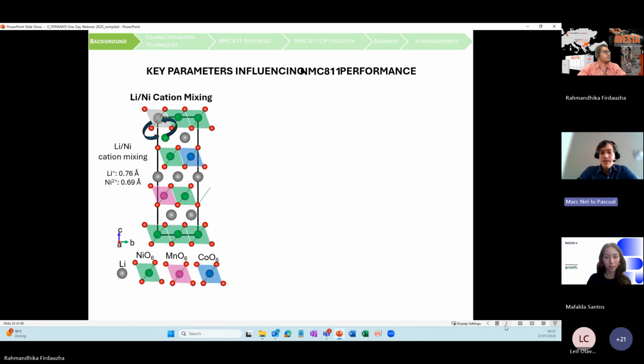Okay, there are several parameters that affect the performance of the NMC 811. And the first one is the lithium nickel cation mixing. This is an effect that occurs when the lithium and the nickel exchange positions in the crystal structure. This happens when the nickel is in a 2+ oxidation state, showing a similar ionic radius as the lithium.